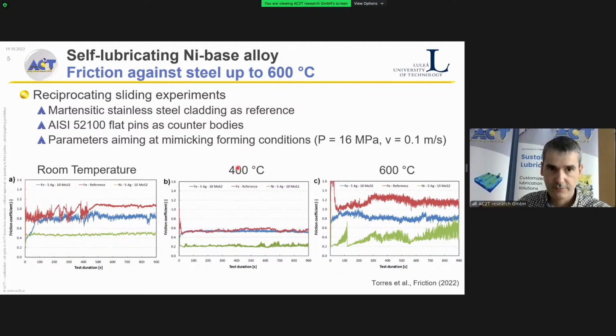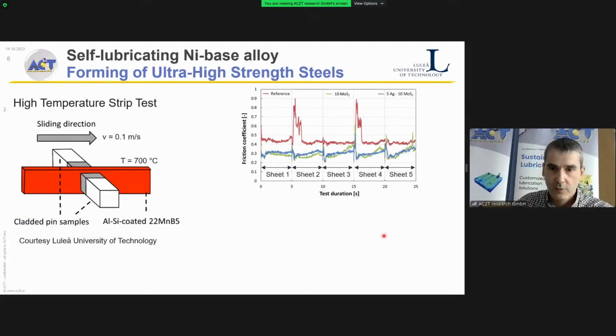For example, look here at 400 degrees, we can have a metal-to-metal contact at 400 degrees without any lubricant and a steady coefficient of friction of 0.2 compared to close to 0.6 for the martensitic stainless steel. So very good friction performance, and at 600 degrees still managed to get some good performance, much better than the reference alloy, but already struggles a bit. We also try